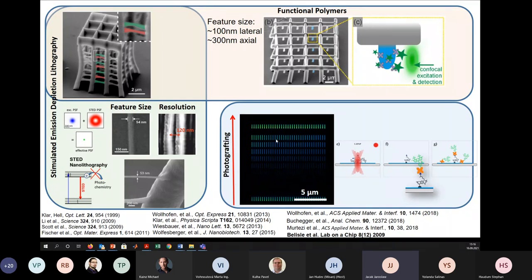So we use photochemistry in order to paint molecules on top of our surfaces. For example, here what you see is a BSA structured, BSA passivated surface, and on BSA we used fluorescently labeled molecules, and we bleached the fluorophores. Due to the radicals forming from photobleaching, the fluorophores interacted with the surface and were immobilized exactly where we wanted them, exactly where the focus beam was.